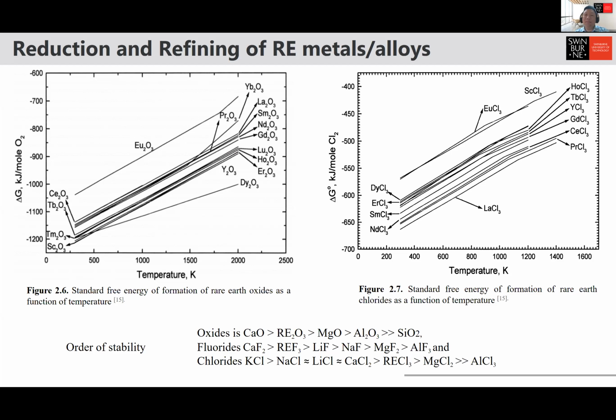And if you reduce them, you won't reduce and get the rare earth oxide, right? You'll get the less stable oxide, such as iron and so on. So basically it's difficult for you to use a direct reduction of slag. So you have to either dissolve it in salt, yeah, that's the salt electrolysis process, or you form it into other compounds such as fluorides and chlorides before you reduce them.